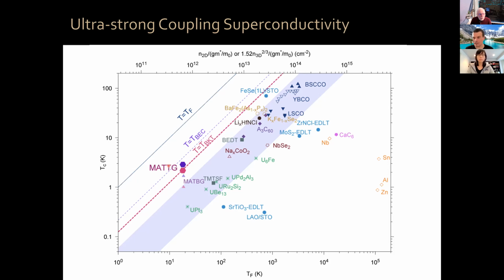Magic angle twisted trilayer graphene is even more strongly coupled than the bilayer case, and it's in fact the strongest coupled superconductor that exists in the world, okay? Only recently, Iwasa's group has posted in the archive that lithium doped zirconium nitride chloride is another system where you can reach this line, okay, of ultra strong coupling superconductivity.